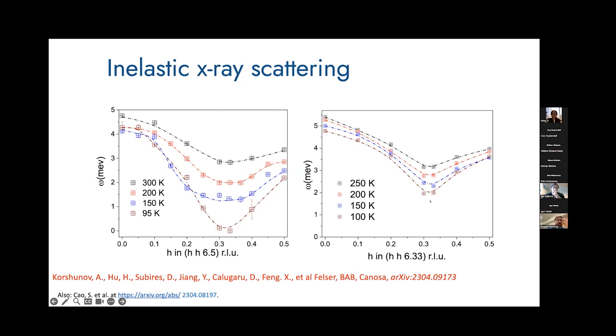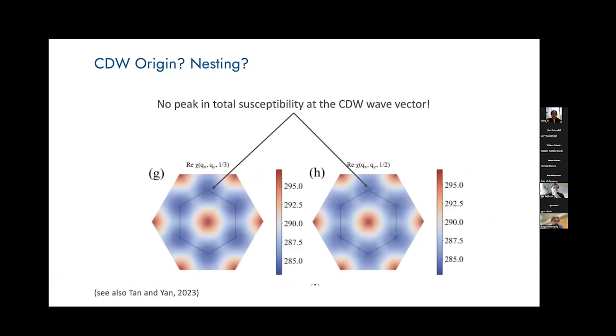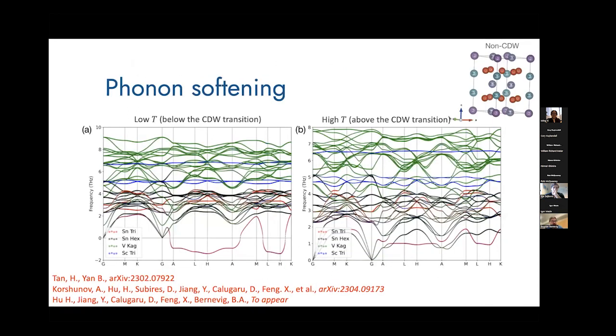So trying to explain this, what I found at the time, and still find quite remarkable, as an experimental fact, is what I'm going to try to present now. We're looking for nesting origins, etc. But you look at the total susceptibility, and there is no peak in the total susceptibility at the CDW wave vector. So this can't be the explanation, at least for the total susceptibility. And then, of course, a lot of the work that we did was based on Yi's and Xiaolong's models for phonons that get you the phonon spectrum at low temperature and high temperature.